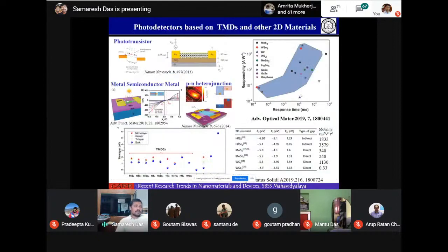So this is the overview of photodetectors made by different 2D materials, and you can see the responsivity can go up to 10 to the power 5 ampere per watt. You can imagine, it is very high. Whereas for a silicon photodiode, the responsivity is less than 1 ampere per watt. By using these 2D materials, you can reach very high responsivity. So these are very useful for optoelectronic devices.